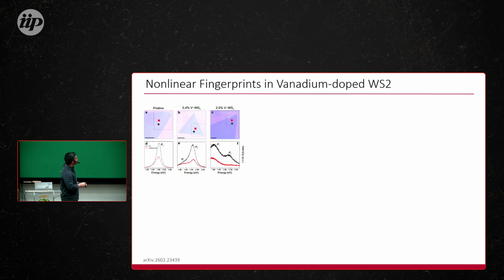So this is the electronic spectrum. Here is the exciton. We can see it very nicely for this WS2, at about 1.95 eV in this sample. And then we start to see some small shoulders over here, which are related with the vanadium, the defect. And then when you have a very high concentration, we can see how it is. You can notice here the red and black spectra are from different points on the sample, and you will understand why I'm showing those two.